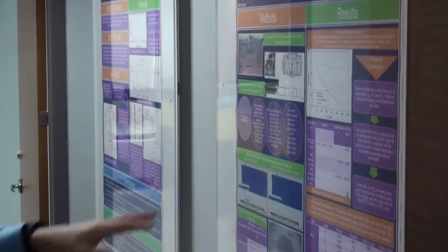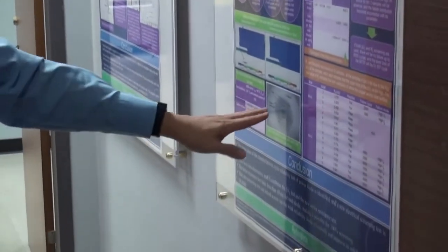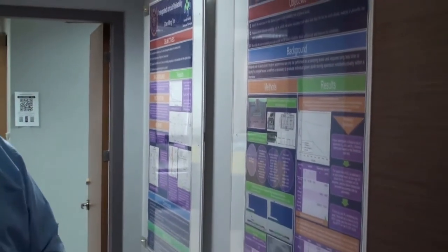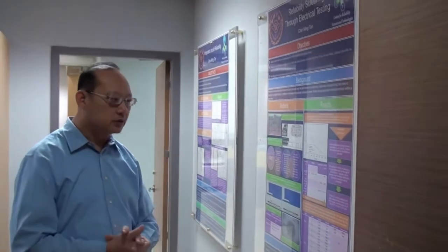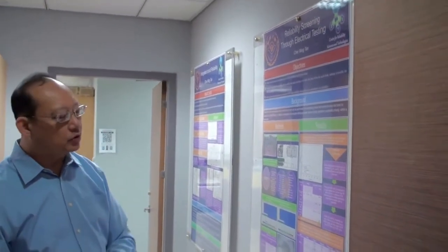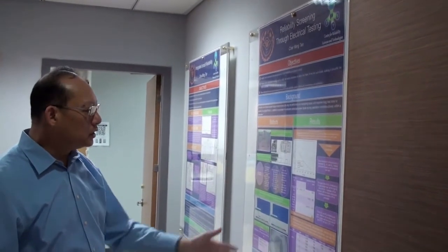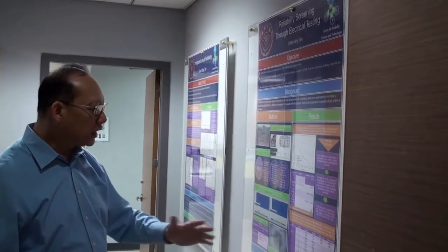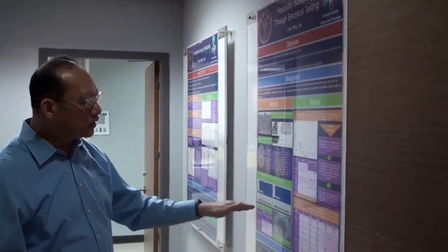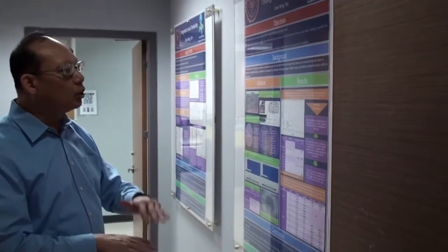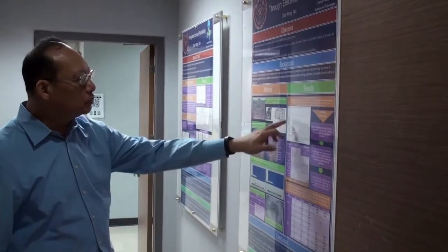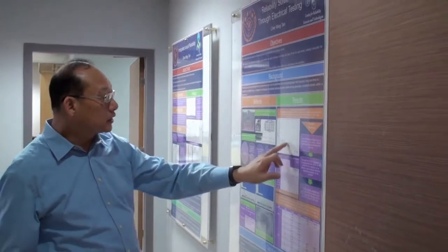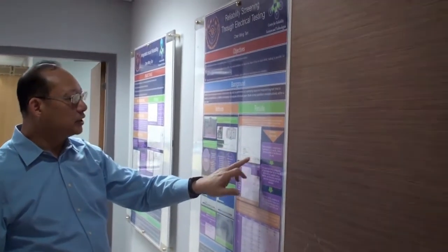and cathode. So what they have done previously with this company is use an X-ray to screen it, so that when the solder preforms are misaligned, they can stop shipping to a customer. But this is very time consuming. So what I've done with the company is to develop an electrical method whereby, without looking at the X-ray, they are able to know whether the solder preform has been misaligned or whether there's a contamination in the solder. So initially, when they do the power cycle test, the reliability drops very significantly.